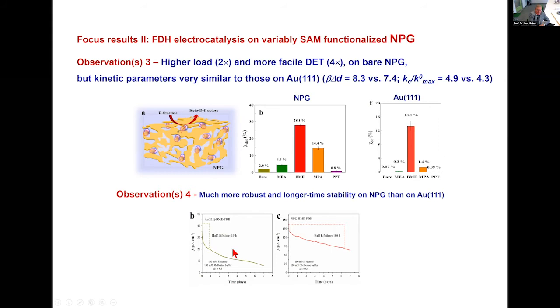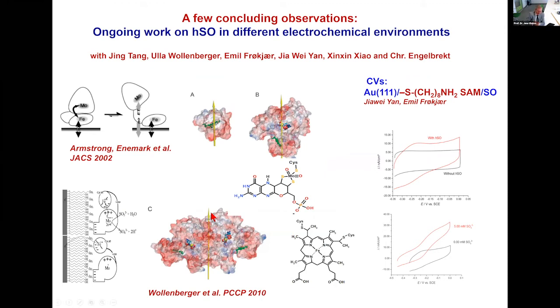What is different, however, is the stability, and it is quite rewarding to see that the half-life was 19 hours on single crystal gold, but it is 150 hours on the nanoporous gold. So this is the sort of results that one would like to see, but maybe more strongly expressed. And one final thing is